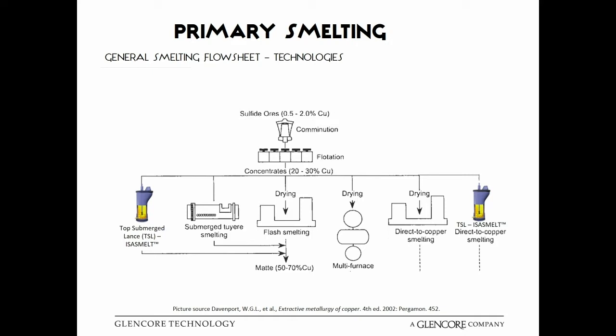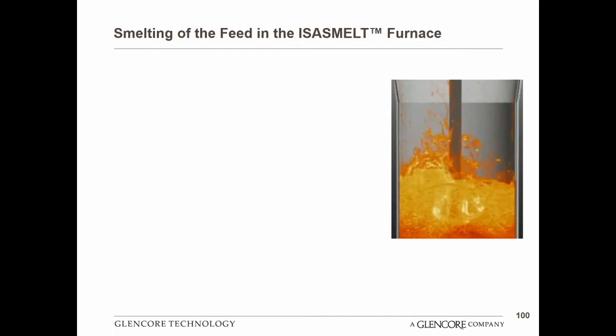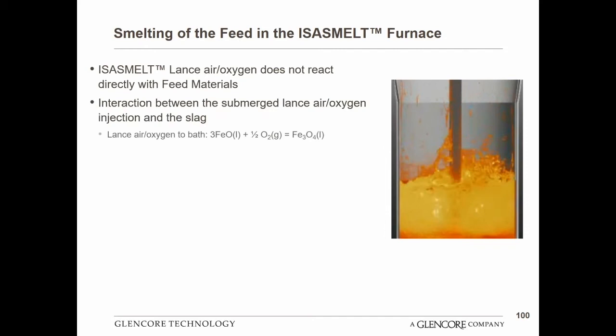So really, when we look at all these technologies, what sets IsaSmelt apart in the bigger picture? And really what sets it apart is what happens with the lance in the center of the vessel. So what we have is a top submerged lance. The lance comes in the center of the vessel, and then through the submergence and the injection of the air and oxygen, provides a vast amount of turbulence within the center of the vessel. And you'll see that this turbulence then allows for the feed materials that drop in to rapidly react with the